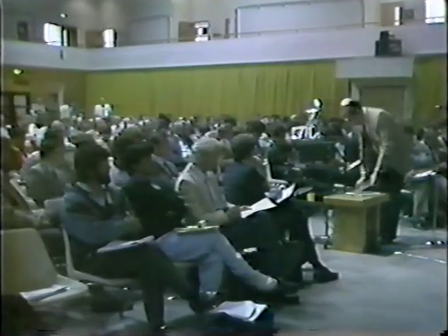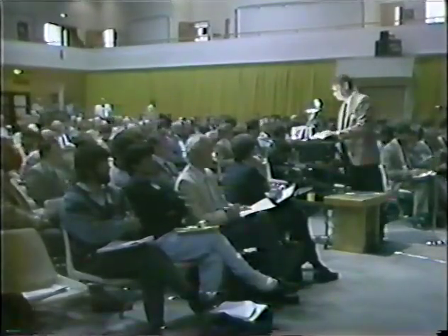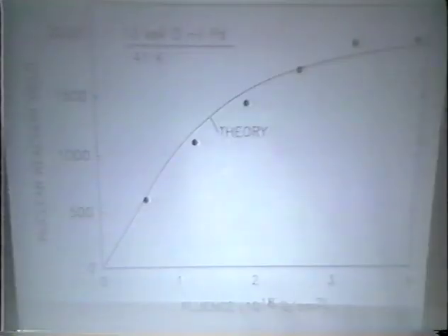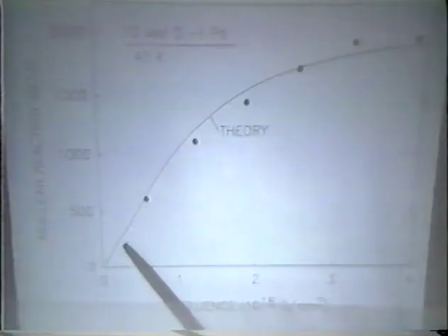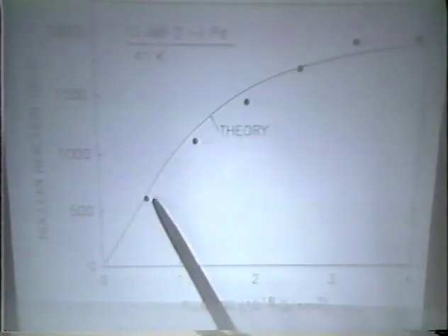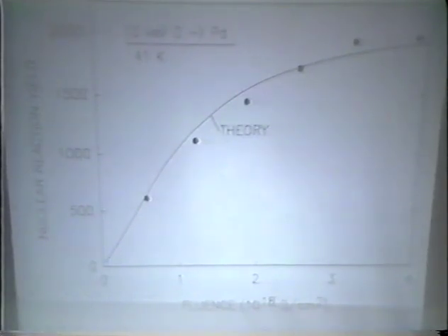Well, the buildup of deuterium at low temperatures during the implantation process, in this case at 40 Kelvin, is shown here. On the horizontal axis, I have plotted the incident fluence of 10 kilovolt deuterium going into the palladium, and this is the nuclear reaction yield, the energetic particles produced by the high energy deuterons striking deuterons already within the material. The key point is that initially we have a more or less linear buildup, which then progressively saturates as one reaches the saturation concentration.